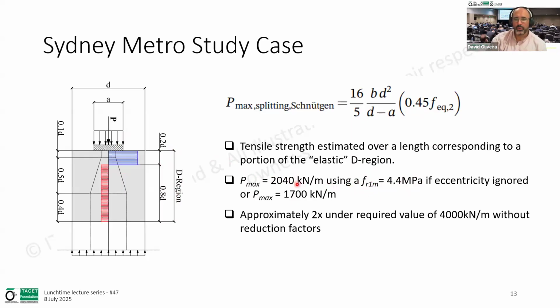We estimate that using the fibers with that mix design we'd only achieve about 2 meganewtons, and this ignores eccentricity. If we introduce eccentricity, we'd only estimate 1.7 meganewtons per meter, which is well below what we needed. And this is not even putting in a factor of safety or a reduction factor. We weren't quite satisfied with this, so we started looking at how we can improve this.